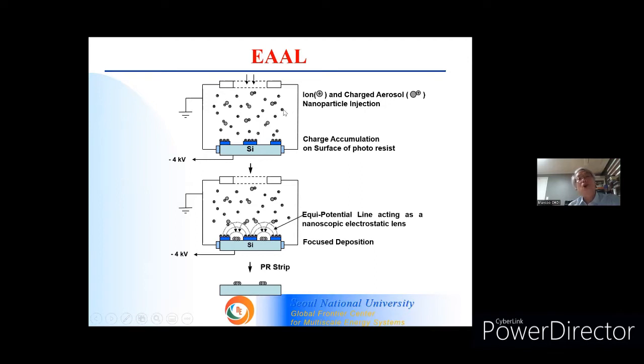But as you know, the ion should have much larger mobility than charged aerosol. That means under the given electric field, ions should have much larger velocity than charged aerosols. That means ions first arrive on the surface of the pre-patterned photoresist pre-patterned silicon substrate before charged aerosols are approaching. That means now ions should accumulate on the dielectric surface of the PMMA photoresist before charged aerosols are approaching.